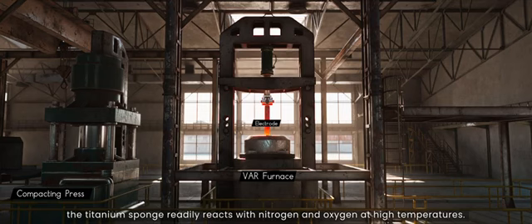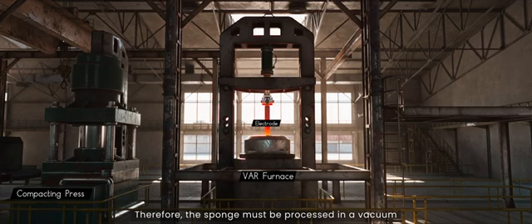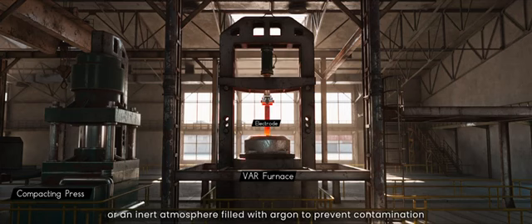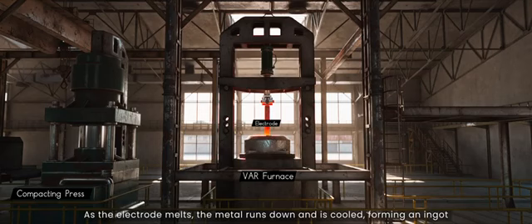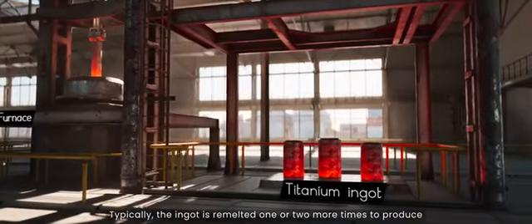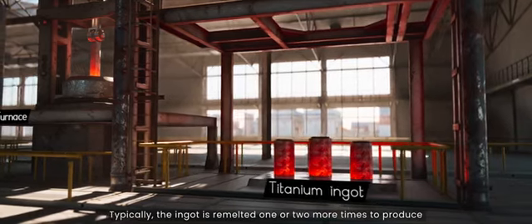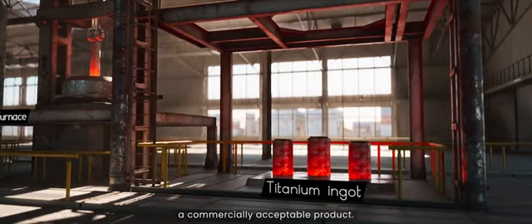The titanium sponge readily reacts with the nitrogen and oxygen at high temperatures. Therefore, the sponge must be processed in a vacuum or an inert atmosphere filled with argon to prevent contamination. As the electrode melts, the metal runs down and is cooled, forming an ingot. Typically, the ingot is remelted 1 or 2 more times to produce a commercially acceptable product.